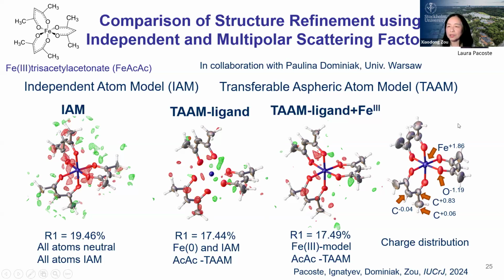So this is how the charge really looks. This is without refinement. You see that iron we find is 1.86, and the oxygen is about -1.2, and then the carbon is positively charged. Then we go further, and it's almost 0. So this is the distribution of charge, even for the iron 3+ atoms.